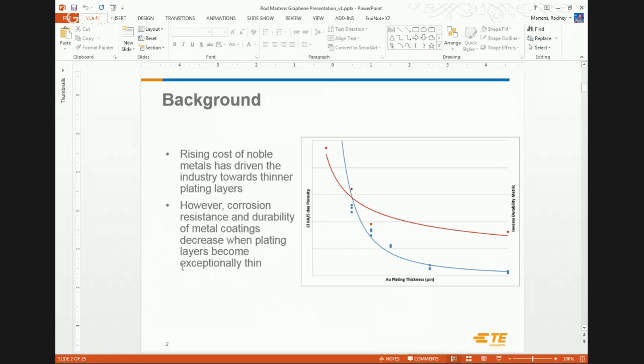Of course, the problem here is that gold's expensive, and as engineers, we're trying to optimize cost in any way that we can. So we're trying to get thinner layers of gold to perform at the same level. As we get thinner and thinner in gold, two of the things we get concerned about: thin layers of gold don't completely cover a surface. They're somewhat porous, and they can allow the substrate to be exposed to a corrosive environment. You get some insulating films on the surface, and then you're having to replug your connector to make it work.